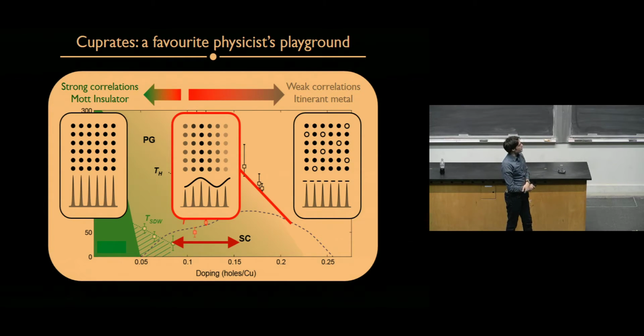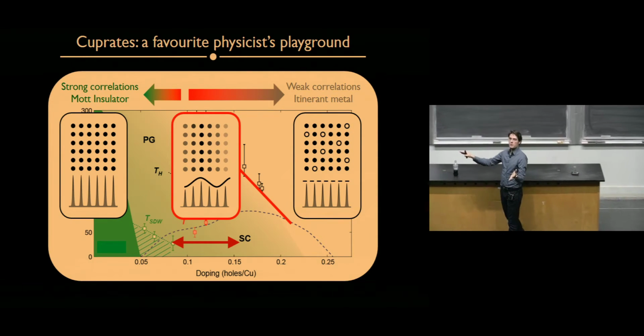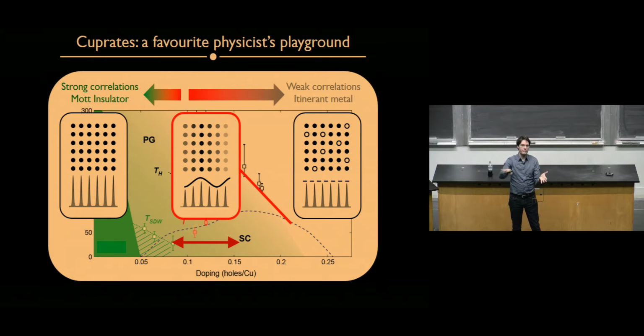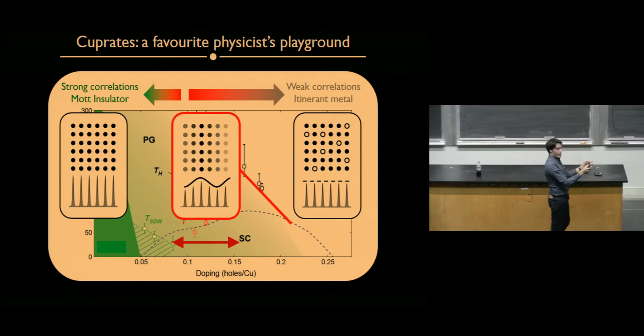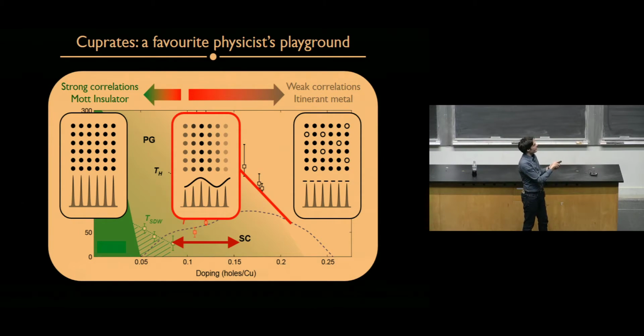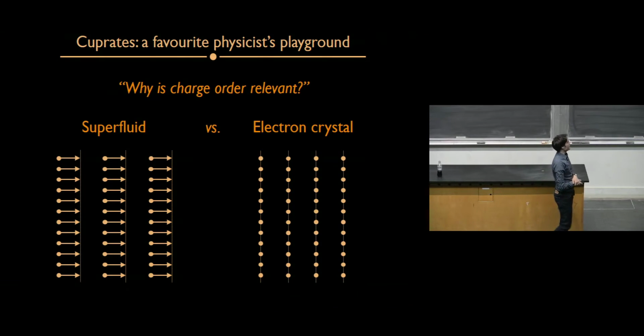And here in the middle, which is the underdoped region, you have some carriers, you've doped some holes there, but not enough to create this electron liquid. And what happens here is that these holes actually crystallize into static orders, which take the form of a modulation of the charge density, okay? So they're not as extreme as this case, where you have one electron per copper site. In this case, you have a more gradual modulation of the charge density, but still a periodic object and static. And this is called charge order, which is what I'm going to talk about today.